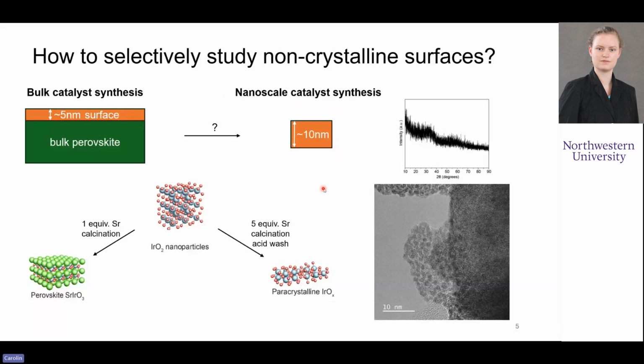And so we were able to synthesize materials like this, starting from the base iridium oxide. It turns out if you use your standard equivalent of strontium, on calcination, you form the perovskite strontium iridate that we've seen before. If you use a large excess of strontium, that intercalates and goes into all those iridium nanoparticles. And when you then wash that out with acid, you are left with this iridium oxide structure that has no bulk crystallinity to it. You can see that in the powder XRD pattern that is almost featureless.